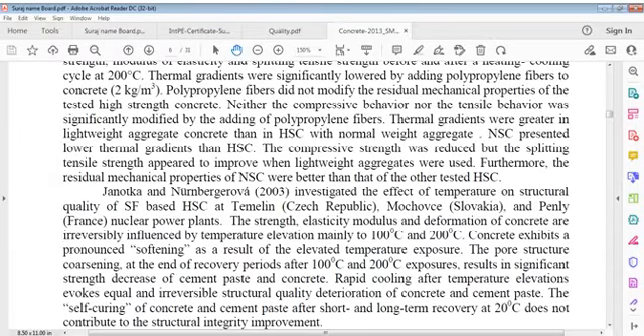Thermal gradients were significantly lowered by adding polypropylene fibers to concrete, 2 kg per cubic meter. Polypropylene fibers did not modify residual mechanical properties of tested high-strength concrete. Neither compressive behavior nor tensile behavior was significantly modified by adding polypropylene fibers.